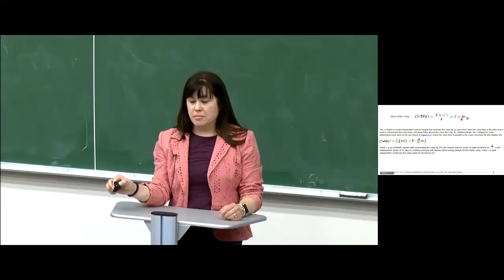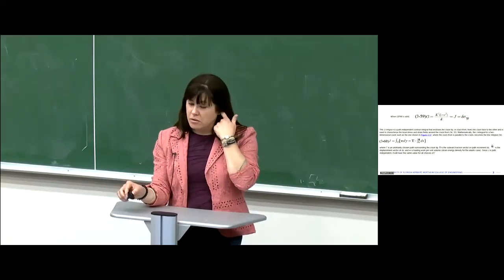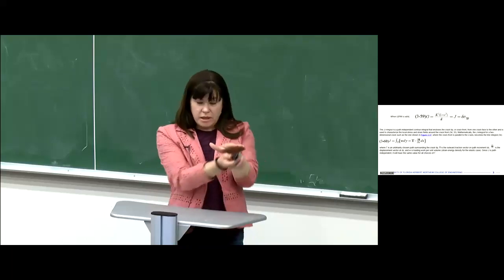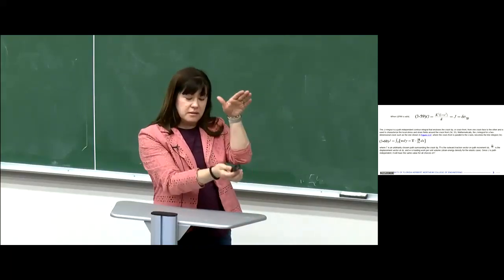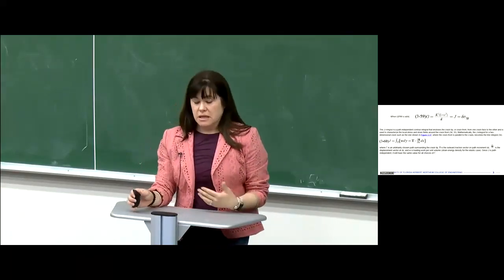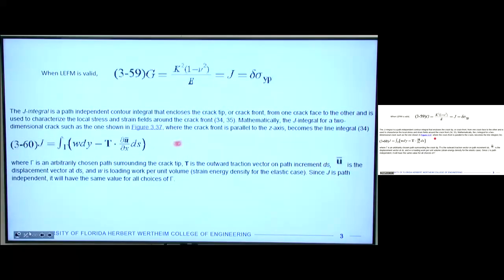But we're going to ignore that part for today. We're just going to talk about J. And so we know that when the crack opens, then there's strain energy released. And so that strain energy released must also be balanced with what's happening in the rest of the material around the crack. So that's the origin of this J integral, or what's shown here in the middle of the screen.